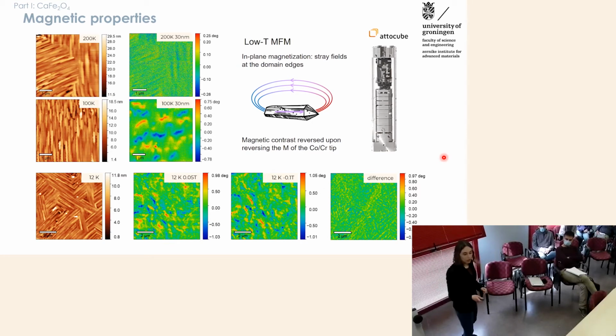So this was quite interesting because it was confirming our idea of this magnetic anisotropy along the easy axis, and also that indeed there are these chains of spins along the crystal needles. And the next experiment that we decided to do on these films, which gives quite a lot of information on the magnetic anisotropy and the magnetic properties, are some spin Hall magnetoresistance measurements. So these are more spin transport measurements, and I will now explain briefly how they work.